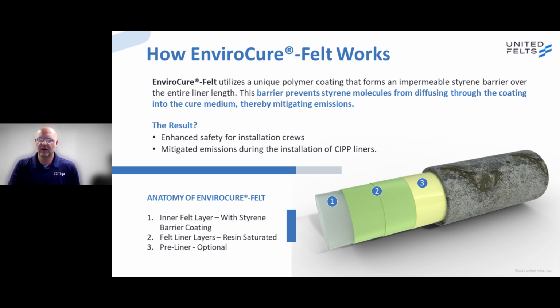The second layer: multiple layers of polyester felt can be added in order to increase the liner thickness to the required design thickness. In addition to polyester felt, we can include layers of our fiberglass reinforced felt if the pressure sewer or the RP products are an option for this particular job. And the third layer is an optional pre-liner. The pre-liner is not necessarily required for the EnviroCure system, but it does work quite well to prevent any sort of styrene emissions from transferring up lateral connections, or to also contain raw resin that may be present in the down tube or the inversion tail of the liner.